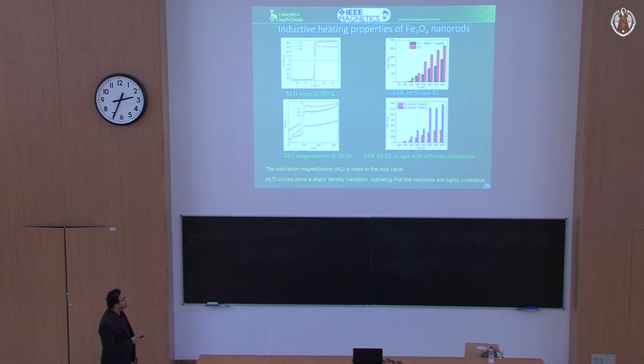The other thing is this curve here, magnetization versus temperature. It turns out that magnetite is an oxide that has a very well-known, celebrated metal insulator transition at low temperatures. This is called the Verwey transition. And this is well studied over the years, the Verwey transition. It's a first order phase transition, so there is a jump in the magnetization. Here's that. This is the Verwey transition, folks.